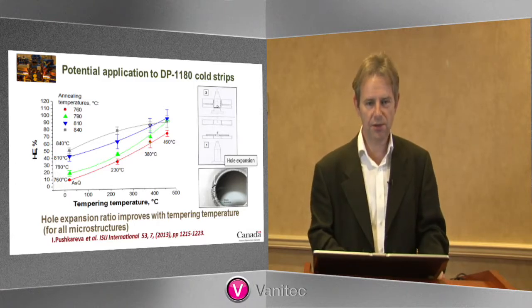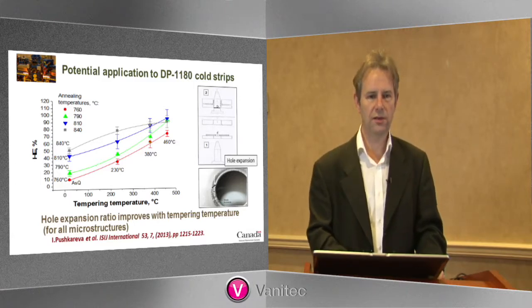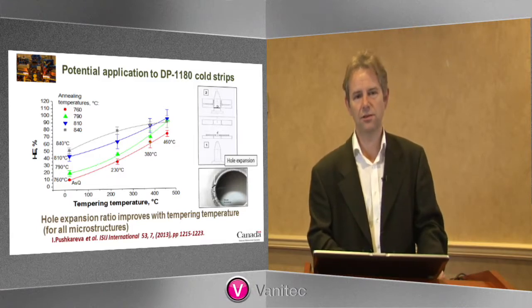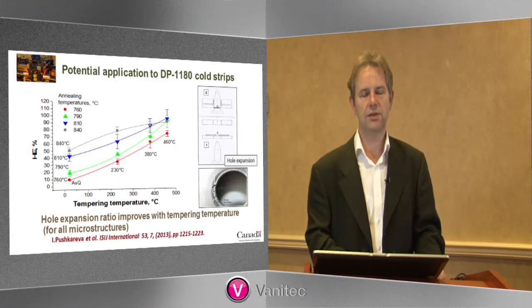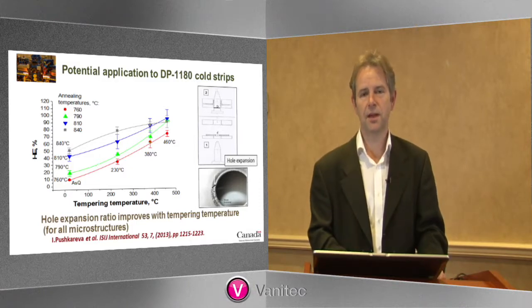Then as you temper the steel, you can see that all of these are improved, and quite significantly. So you can have a very low, very brittle, if you like, steel where you had only 10% of hole expansion capability, and it goes up to 60, 70%, which is very, very good.